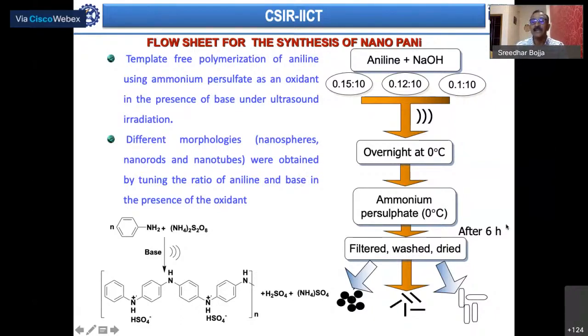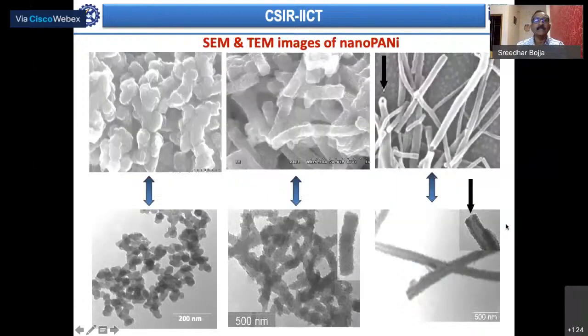When I show you the next slide, it becomes very clear. These are scanning electron microscope images of spheres, rods, and tubes, and these are the TEM images of spheres, rods, and tubes. In these tubes, you can very clearly see the contrast is hollow, because you see a contrast difference here, and they are open-ended. These are a few microns in length.